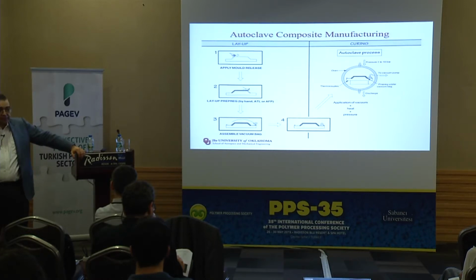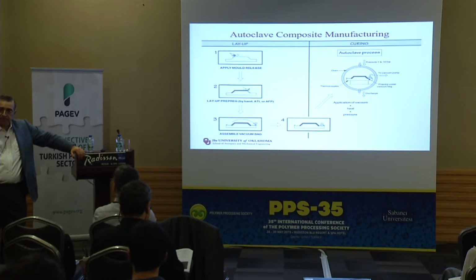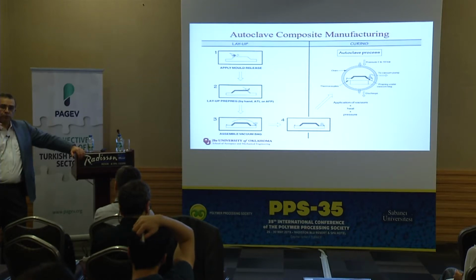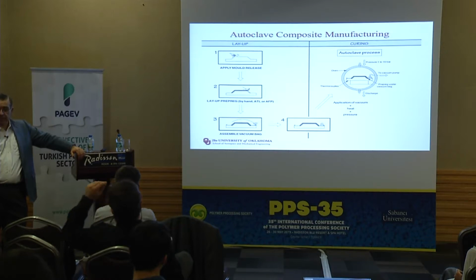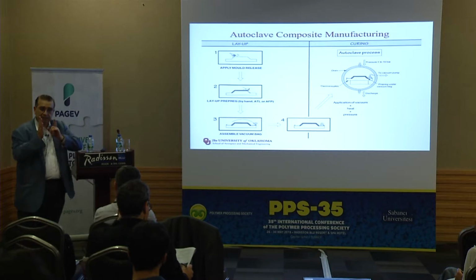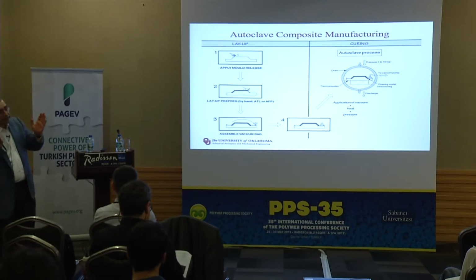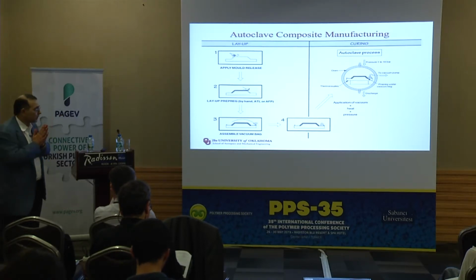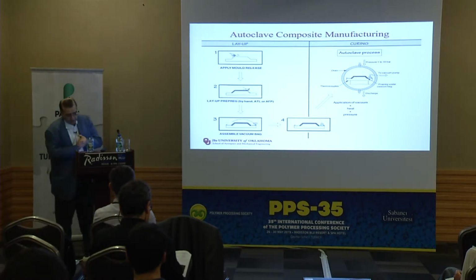There is also another benefit of this applied pressure. If you have voids or air trapped inside, it compacts the voids. Therefore, instead of having 4% void volume fraction, you will end up having 1% voids. Voids will be much smaller in general. Average void size will be smaller. And some of the voids will be collapsed and diffused into the part, so they will essentially disappear. Now, also, as you apply pressure, as the resin flow takes place, some of those voids will move out with the resin as well. So, added pressure essentially gives you increased fiber volume fraction and reduced void content. And therefore, you really need autoclaves for high quality composite laminates used in high performance applications.